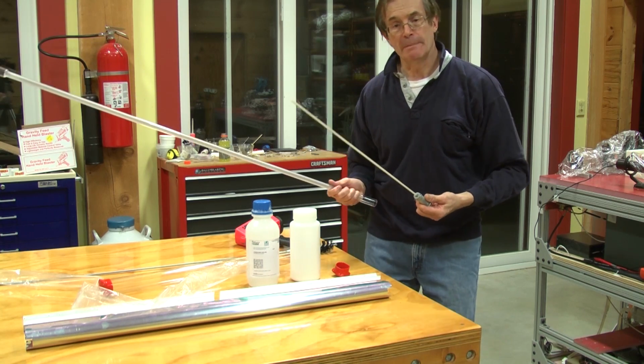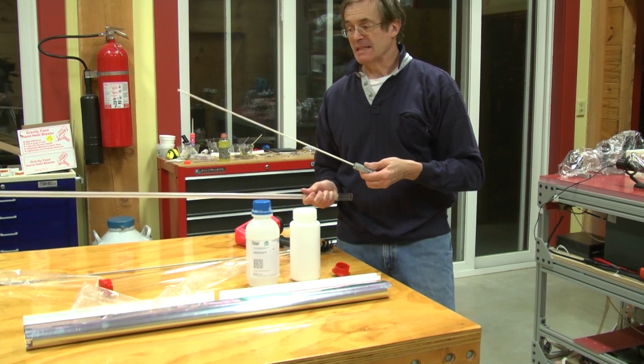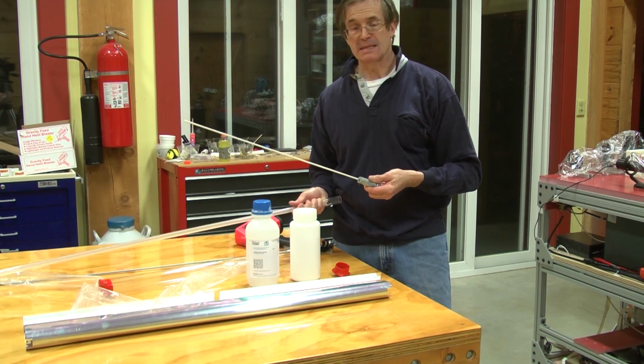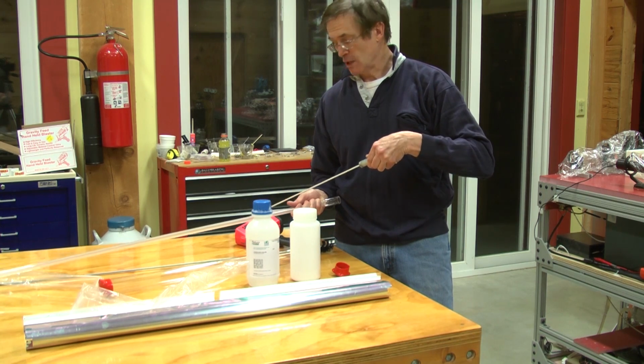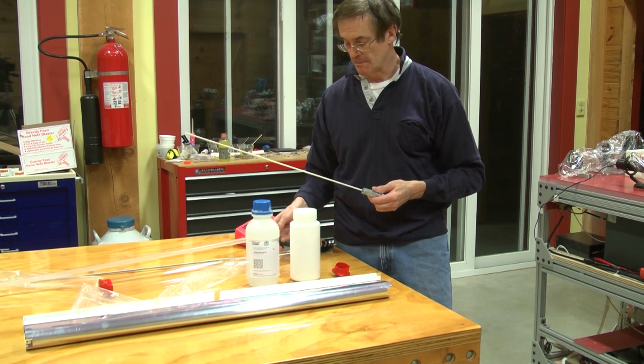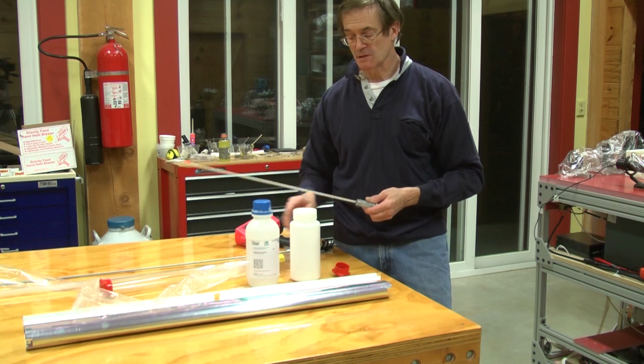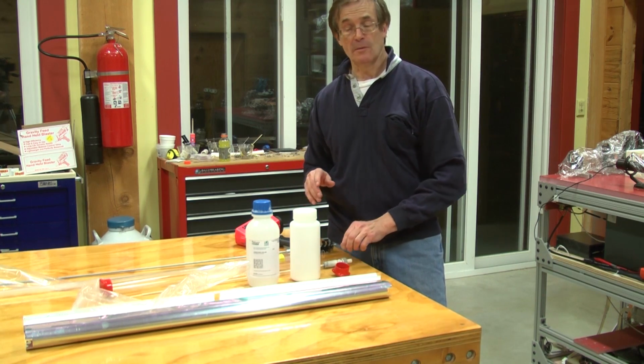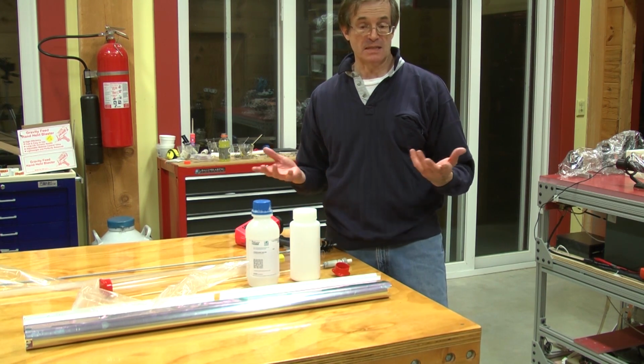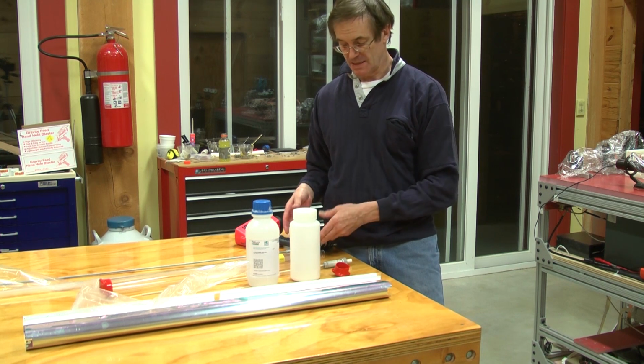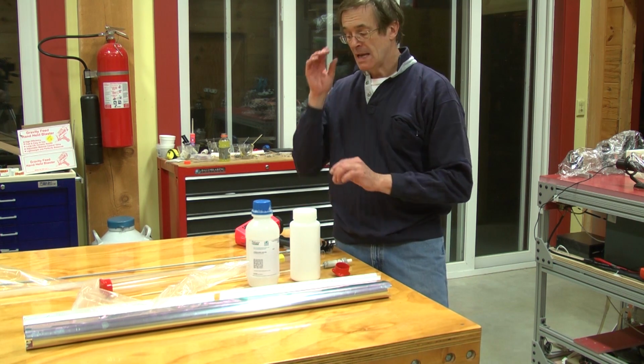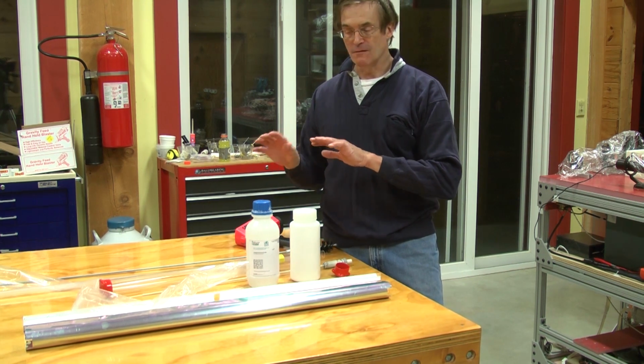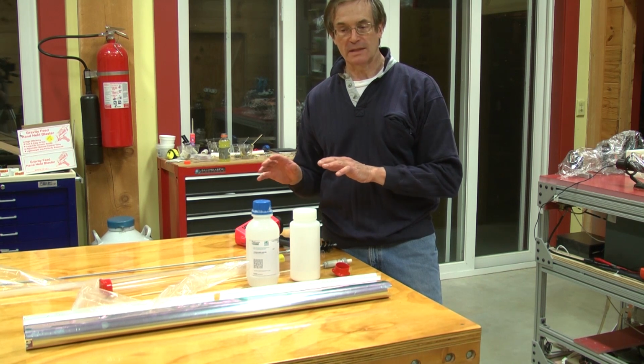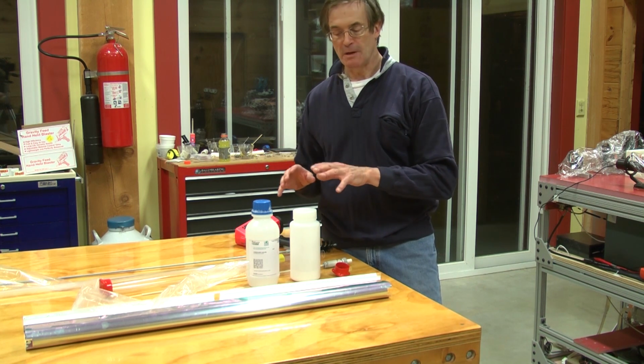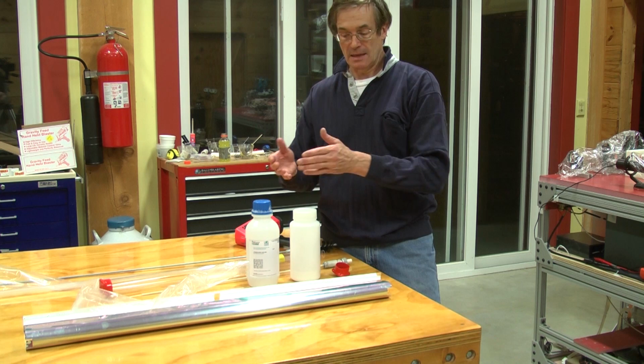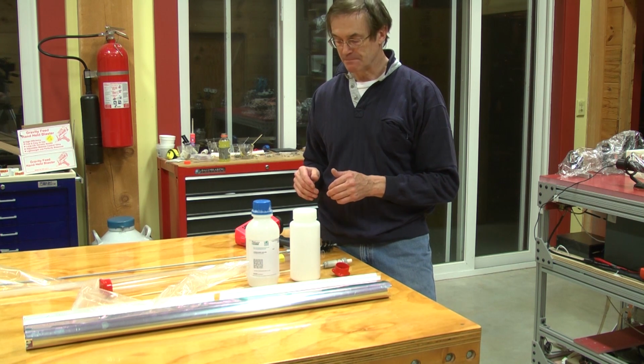End result, I use about a pound of abrasive. It's extremely clean. The only mess that I make from this is the process of just filling the sandblaster. And you end up with a nice coarse finish, and you can even reuse the material from the bag. You can put it right back in the container because it's essentially clean except for a little bit of the silicon oxide from the tube. That matte finish then provides a very good reflective diffuser, much better than the hydrofluoric acid used, and obviously you don't have to get hydrofluoric acid.